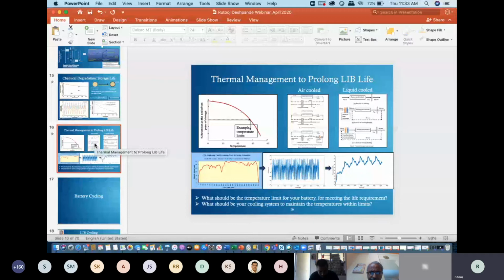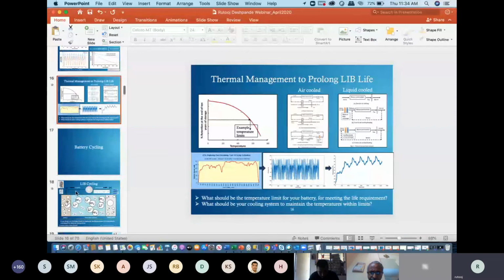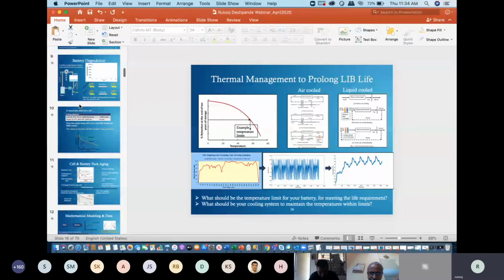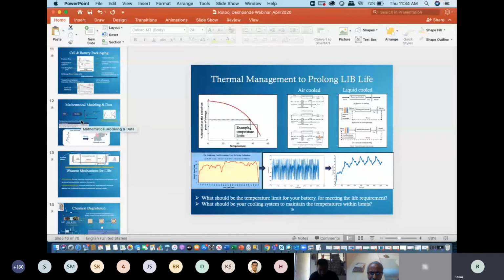If you are using the cell at lower temperatures, at 0 or below sub-zero temperatures, then you have to use it mildly. You cannot use them at the same rates that you would use them at 25 degrees Celsius. This would arise especially in North India, where the temperatures tend to go lower. Coming from Detroit, where the temperatures would always be around 0 degrees Celsius or less in winter, we had to be very careful of battery usage below 0. So you may not be able to deliver the same power. You should not use the battery at the same rates at lower temperatures. But if you are not using the battery at lower temperature, you're just cooling it down and then heating it back to 25, it should not affect anything.